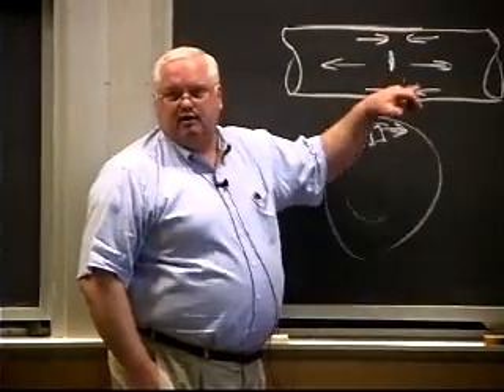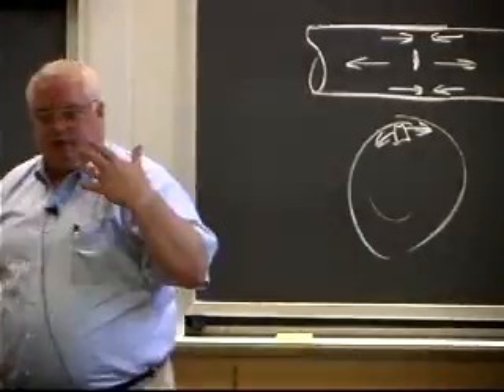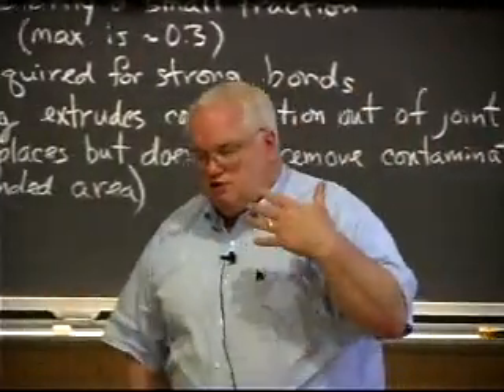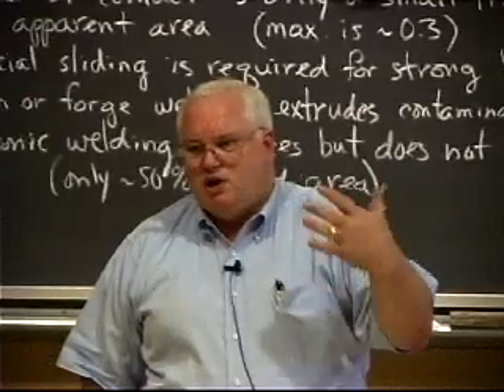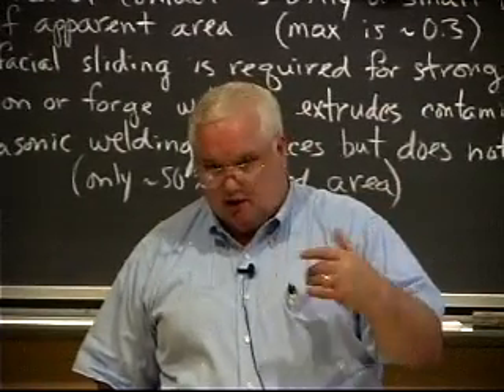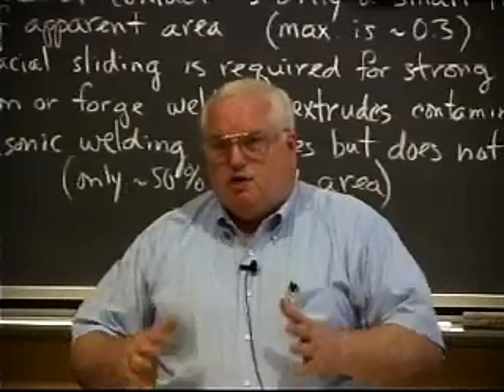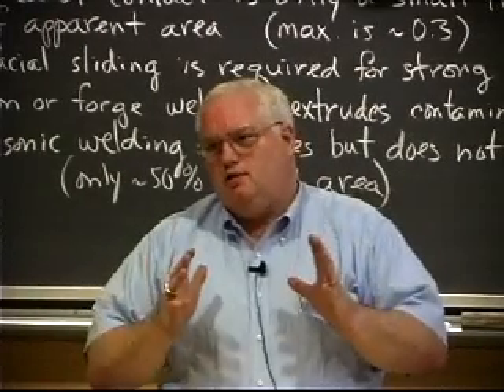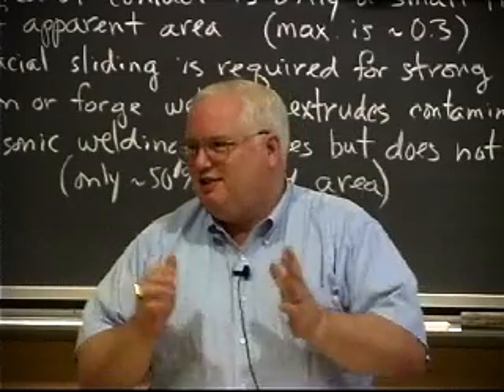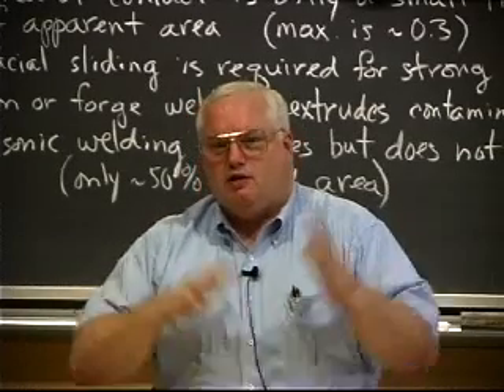It had a defect, and in the lectures, the videotapes, you saw the effect of a flaw initiating a bigger flaw. And so they got what they call a clink defect, and they call it a clink because if you're in the forging shop, you can actually hear this thing. They call it a clink, but it's more like a rifle shot going off. Okay, you can hear the crack pop in because it's a brittle fracture.